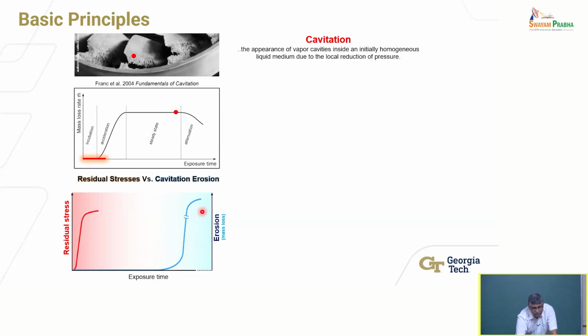Now, if my goal is to erode and remove material, then I'll expose it for a very long time, or some finite amount of time depending on the material. But if I want to simply generate residual stresses, I will expose it for a much shorter time period. I will generate these residual stresses, they'll saturate, and then I stop. And this time is about a 10th to a 20th of the time it takes for me to erode. So it takes a very short amount of time. That's the idea.